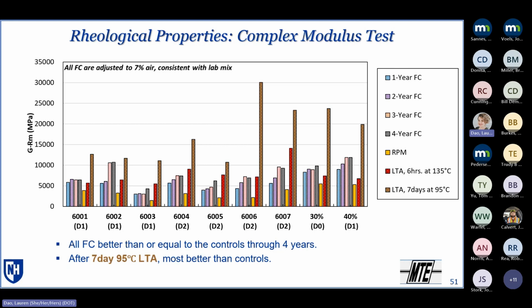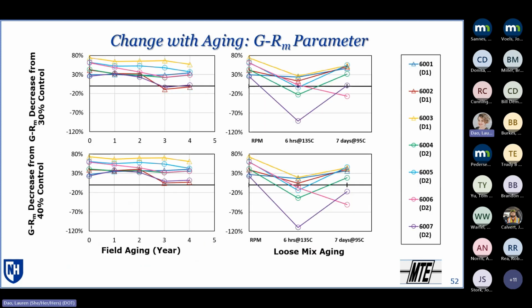But we're seeing with the 7 days at 95, the long-term aging condition, you see quite a jump, but most of these materials are still looking better than the controls from the mix perspective. And then same thing, looking at these specifically in terms of how the Glover-Rowe mix property is changing as compared to the controls. Looking at the field aging, we're not seeing a whole lot of difference in the control comparison over those 4 years. But once we start looking at the lab aging, you're seeing the benefit from the RA decreasing, especially at that longer term aging.